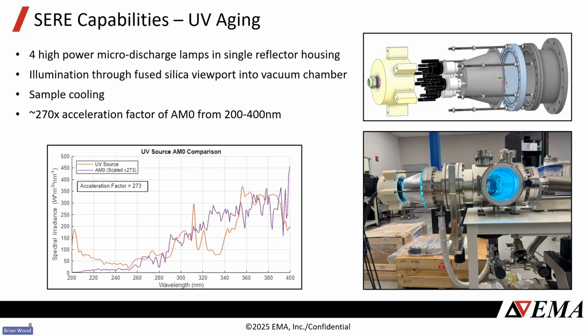And so with UV aging, there are lots of possible needs to do this for specific materials, so we went ahead and made this accelerated UV source. It's shining through a fused silica window into this chamber, and we used our little spectrometer to measure the spectral radiance of the source. That bottom graph is the AM0 in purple, and our UV source, where the AM0 is scaled, in this case 273 times, just to give you a sense of how much it matches the AM0 per wavelength.